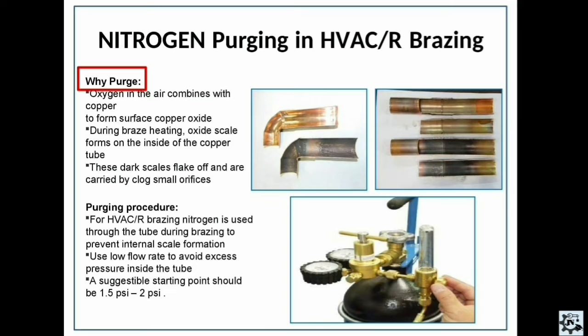Now what is nitrogen purging? Nitrogen purging is the most important process to be followed during the brazing operation to avoid oxide formation during brazing. Take one example. Let's consider we are joining two copper tubes by means of the brazing process without considering the nitrogen purging operation. What happens during the brazing process is that the oxygen in the air combines with the copper to form copper oxide. That means there is oxide formation on the copper surface. So during braze heating, the oxide scale forms inside the copper tube, and these dark scale flakes off and are carried to clog small orifices.